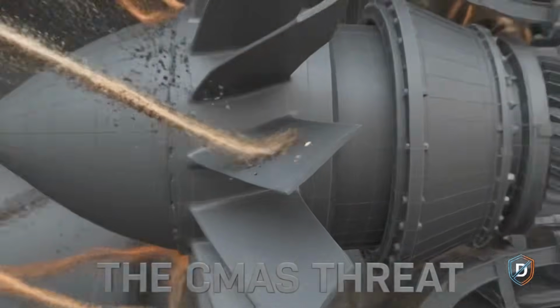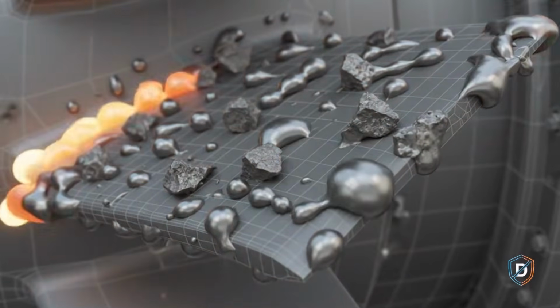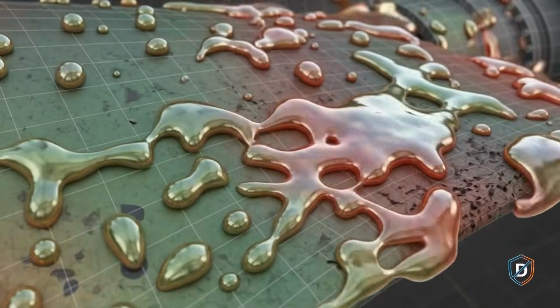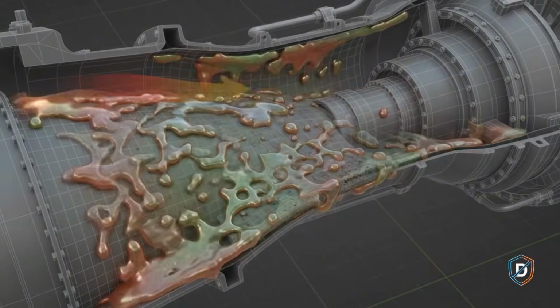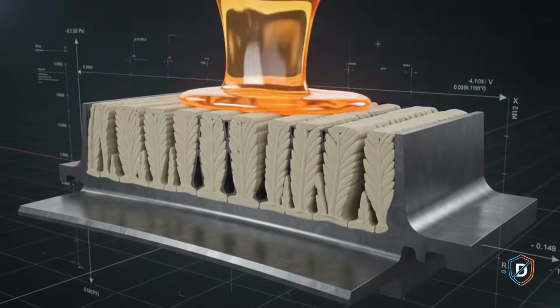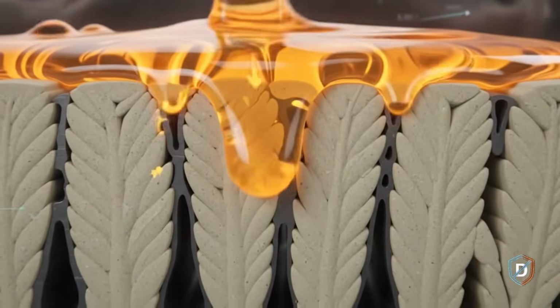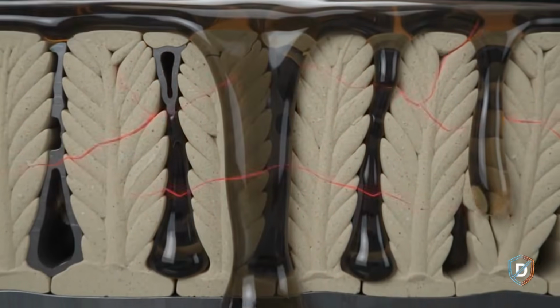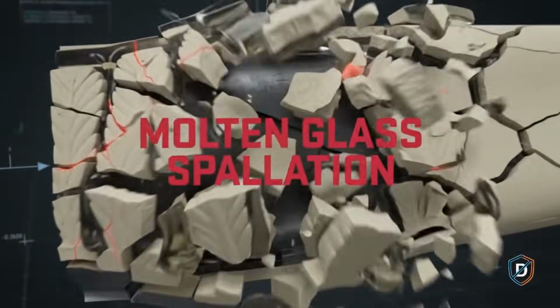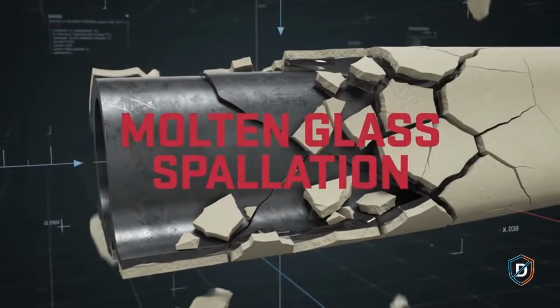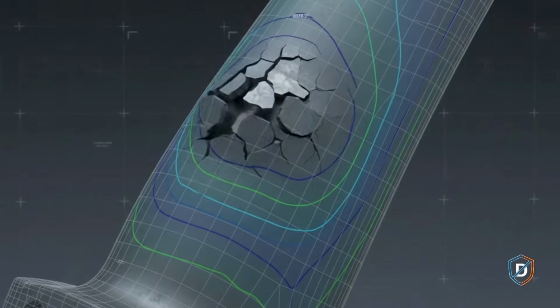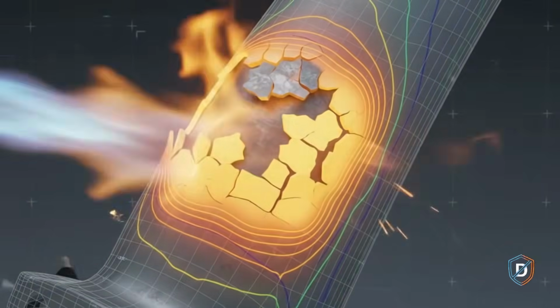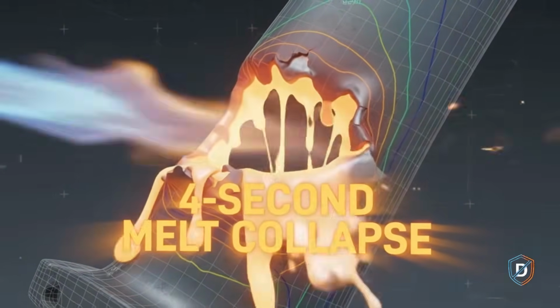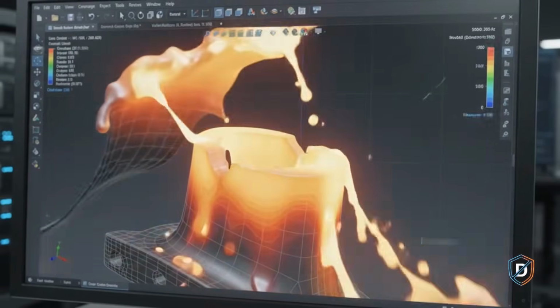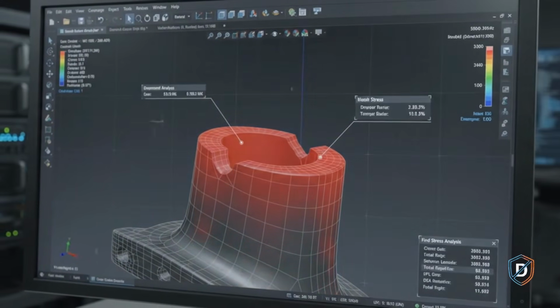But this nanotech shield has a hidden killer, CMAS, a mixture of calcium, magnesium, aluminum, and sand found in atmospheric dust. At turbine heat, sand turns into liquid glass. It seeps between the ceramic feathers, freezes solid, and rips the ceramic off the blade in massive chunks. The instant ceramic flakes off, the raw superalloy behind it melts in less than 4 seconds. This happens under the 2,000-degree gas stream.